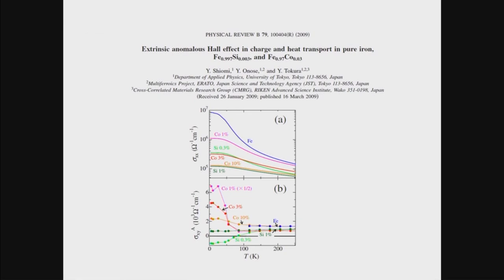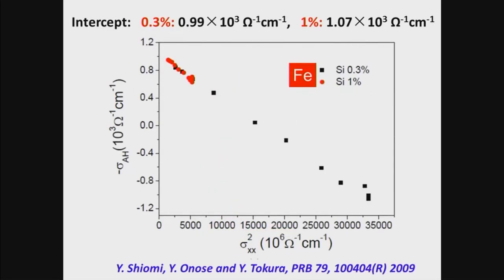Another interesting thing we noticed when we published our paper is another paper from Tokura's group at the University of Tokyo. They were talking about doping silicon in iron, and because you tune the defect, they have the title of extrinsic effect. But we're just using their raw data and plotting it in our way. The low temperature data for 1% of silicon starts from here, 300K is here. And 0.3% of silicon, low temperature data here, and the high temperature data here. And they actually collapse on top of each other. And if you try to see what the intercept is, again, it's 1,000. So this is a kind of strong evidence. This intercept is the Berry curvature, or the intrinsic contribution.